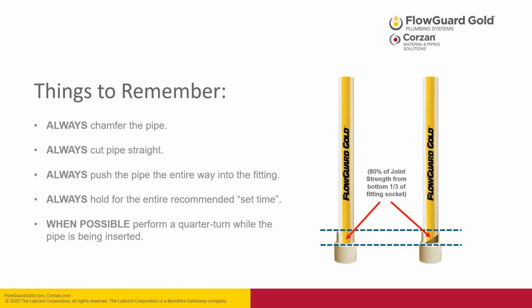With both FlowGuard Gold and Corzan, there are a few things to remember. Always chamfer the pipe. Always cut the pipe straight, and push the pipe the entire way into the fitting. Hold the system together for the entire recommended set time, and when possible, perform a quarter turn while the pipe is being inserted. 80% of the joint strength comes from the bottom third of the fitting socket, which is why it's important to cut the pipe straight and push it the entire way into the fitting.